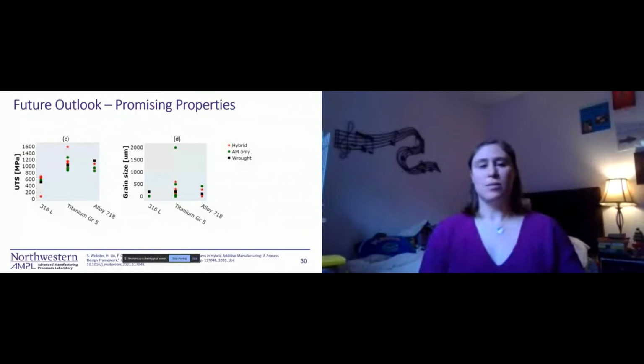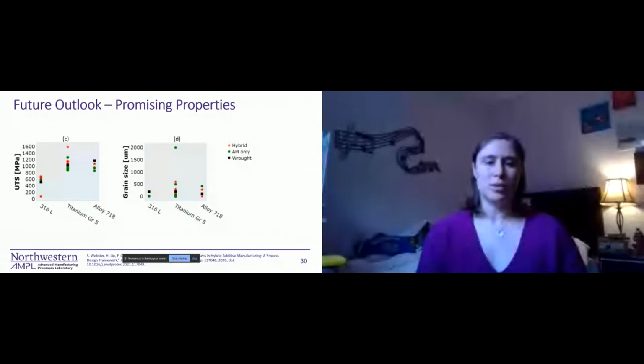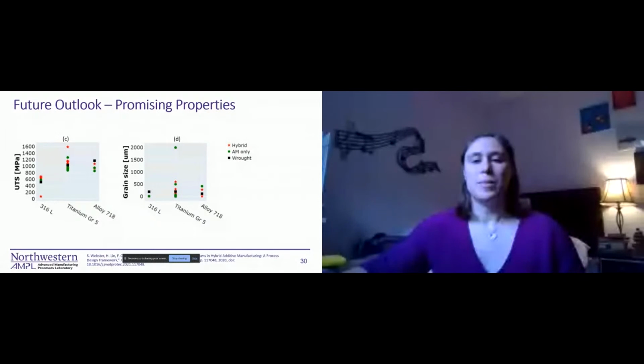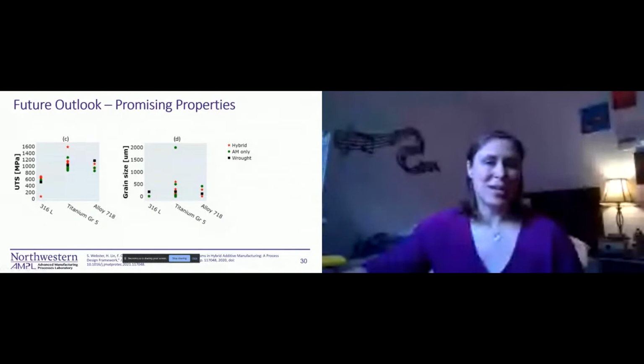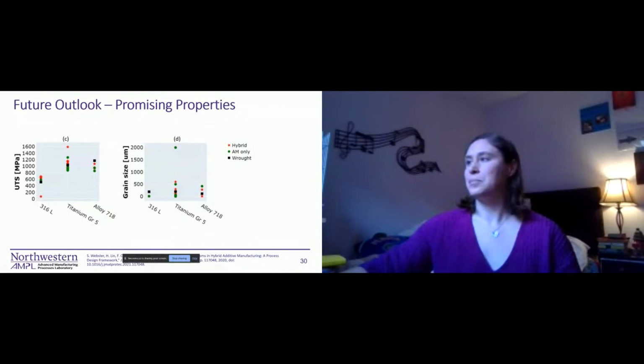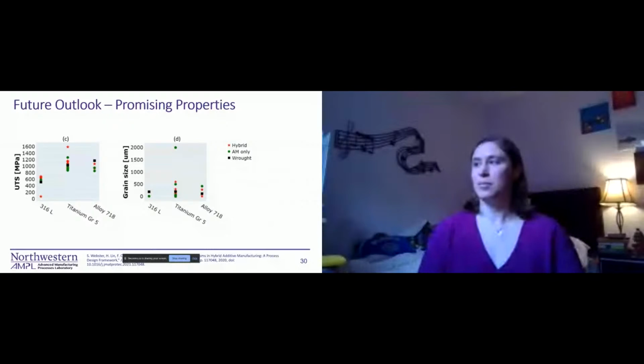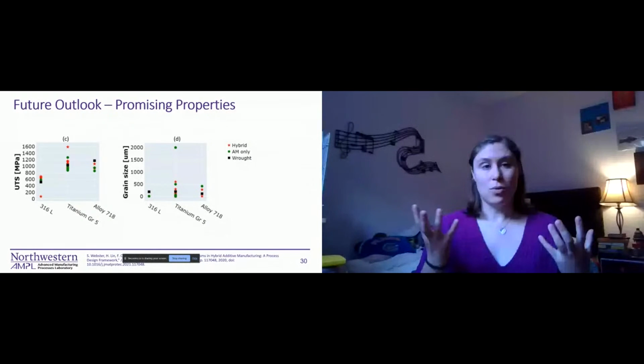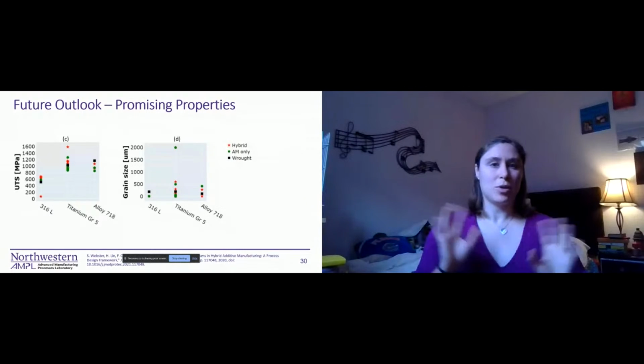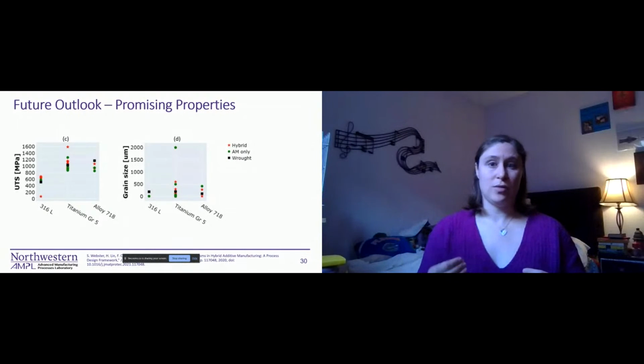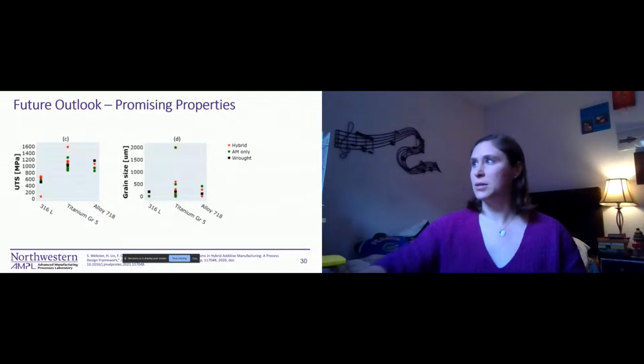We can also see between UTS and grain size, smaller grains were achieved overall for the particular materials presented here. These were the 3 materials that were mainly researched, with the exception of titanium, which has a habit of forming very long beta grains in a material. So overall, there's a very promising outlook for properties that can be achieved with hybrid versus AM only processes.